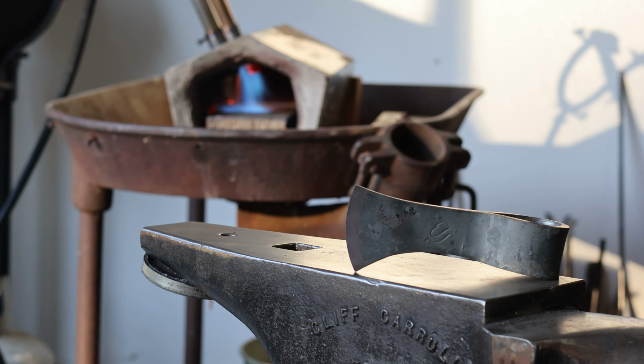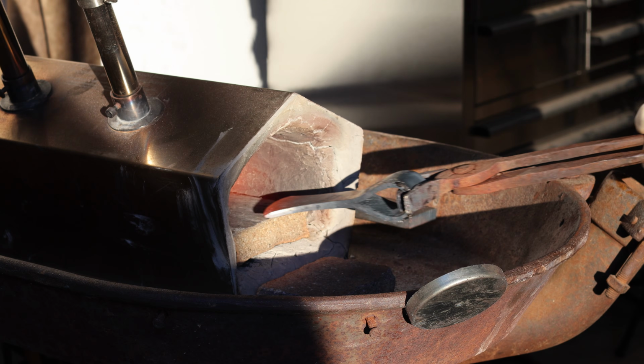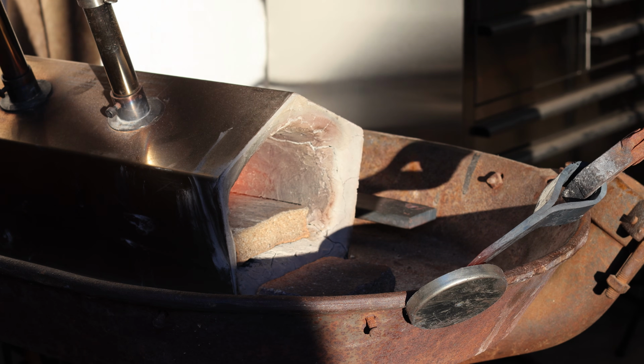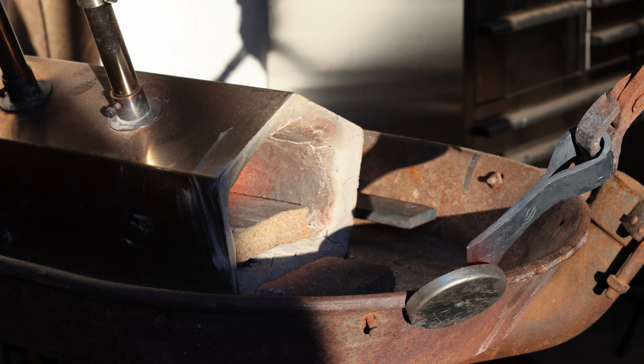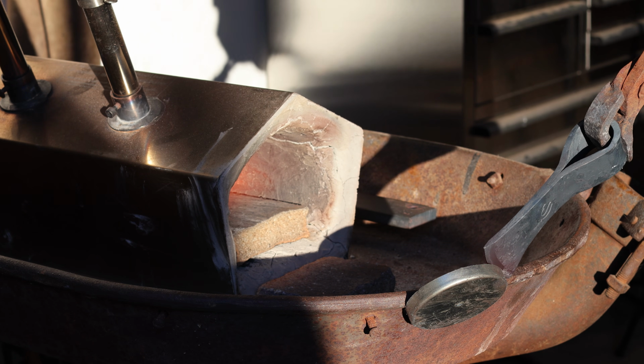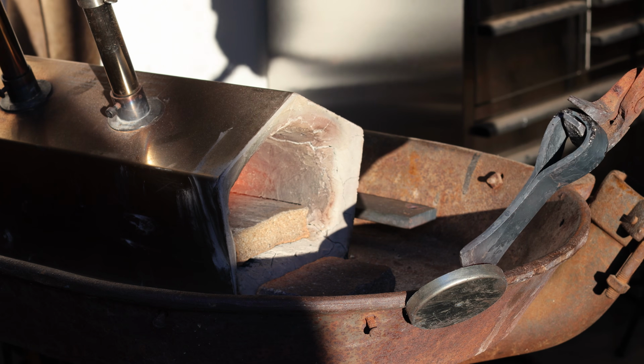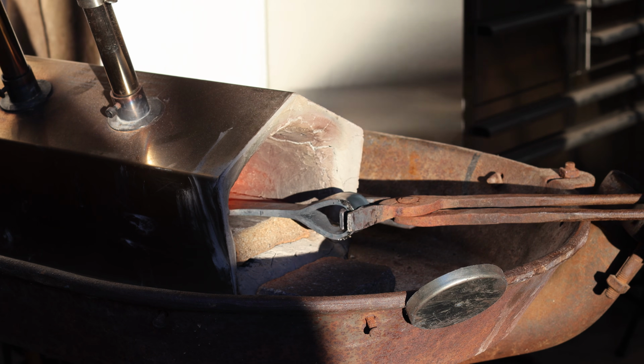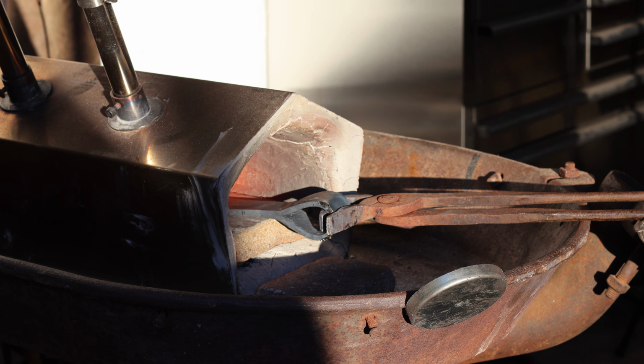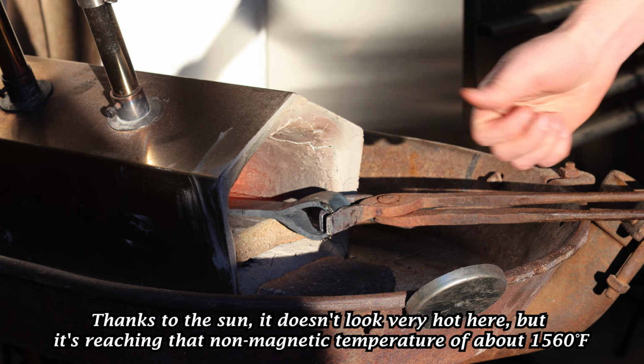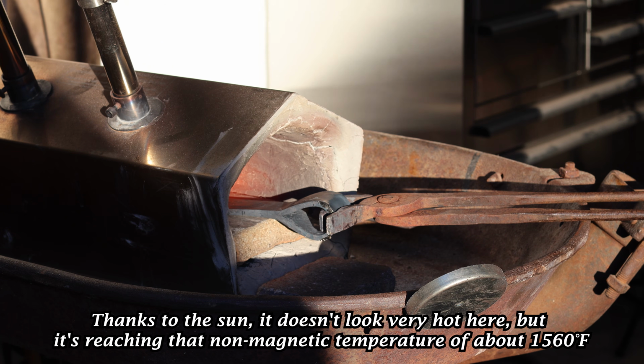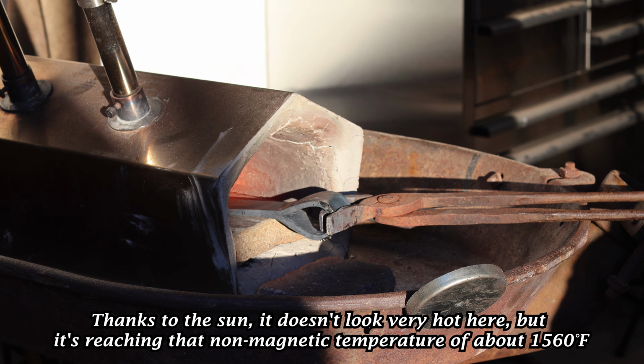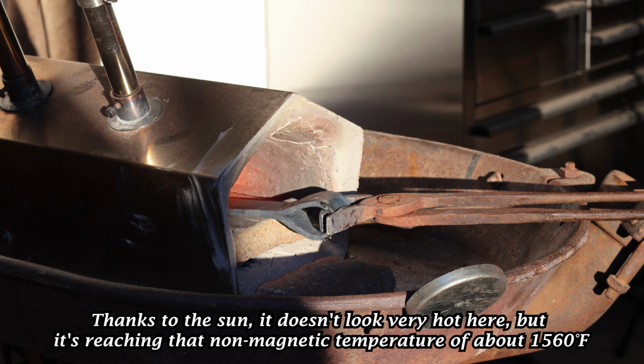All right, so I've got the bevels ground in on this tomahawk, and I've got them ground down to about 1/16 of an inch. I don't want to get it too thin along the edge before I go ahead and heat treat this, because I don't want the edge to be so skinny that it has a propensity to warp. And I'm only going to do an edge quench on this because the only hardenable steel in this tomahawk head is the edge itself, that 1095 bit.